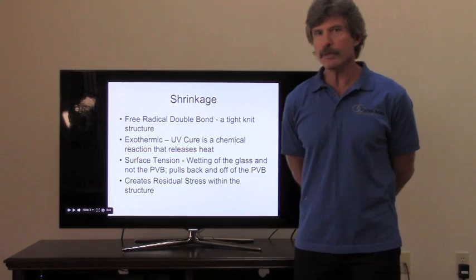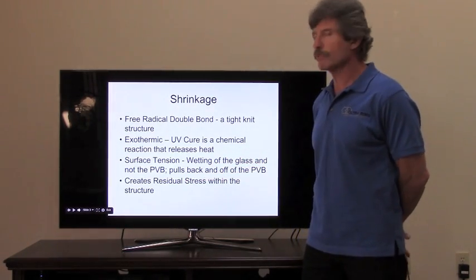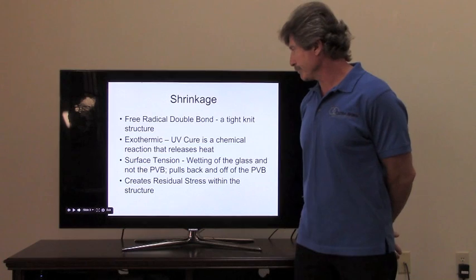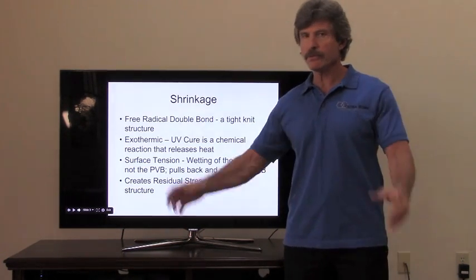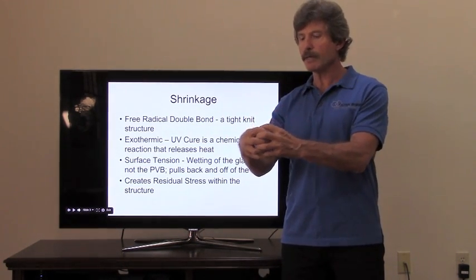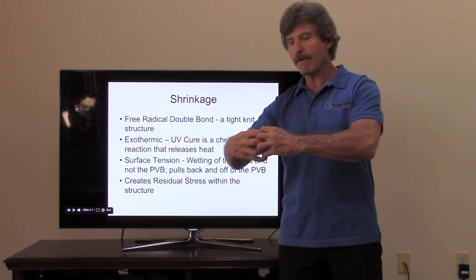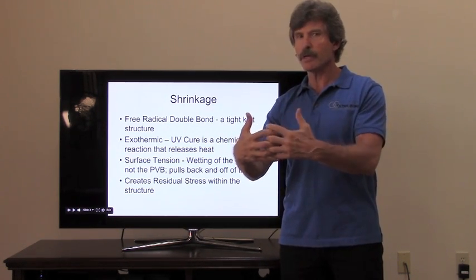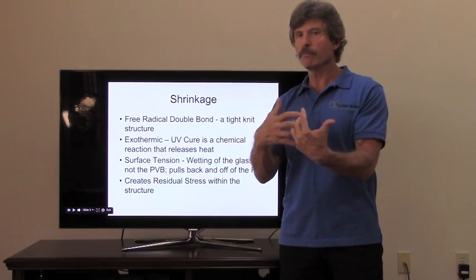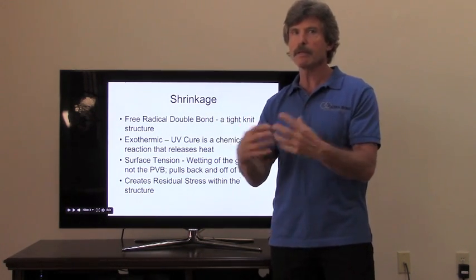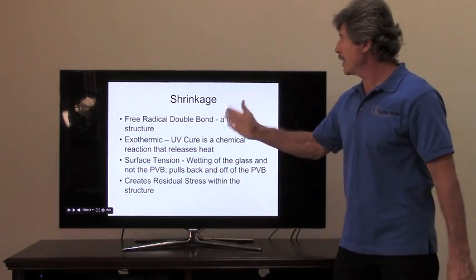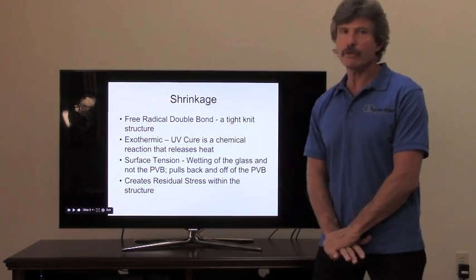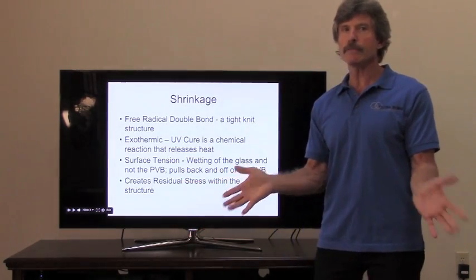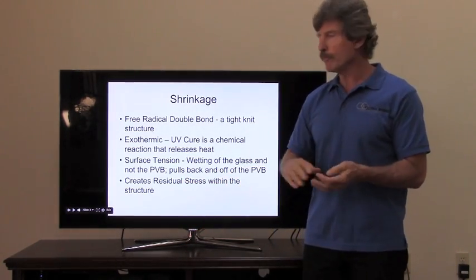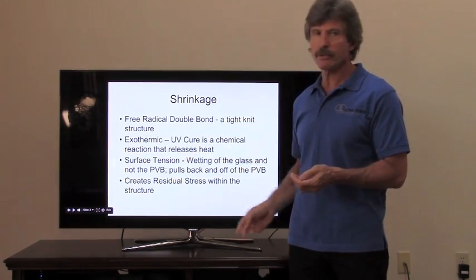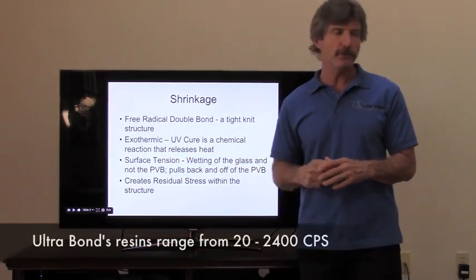What happens when you have shrinkage is it creates residual stress within the structure. Because instead of having a loose bond like this, you've got a tight bond like that. And it doesn't take much stress from temperature change or from the installation stress to start snapping those cross links. So how do you get rid of shrinkage? Well, with a stone break, it's easy. You cure it under pressure, and with a crack, to deal with surface tension, you cure that by viscosity.